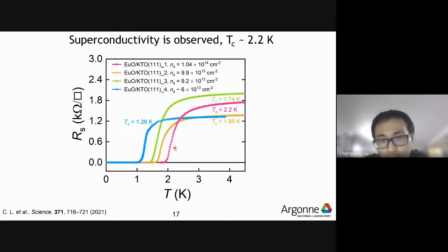And just to remind you, the LAO/STO system showed superconductivity at a temperature of around 200 millikelvin. So this means this KTO interface is showing superconductivity with a Tc about 1 order of magnitude higher than that. This could bring us a lot of opportunities for superconducting device applications or quantum computing using superconducting qubits, because now you don't have to use a dilution fridge to get to the superconducting state. At 2.2 Kelvin, you could just use a regular helium cryostat to achieve this temperature regime.